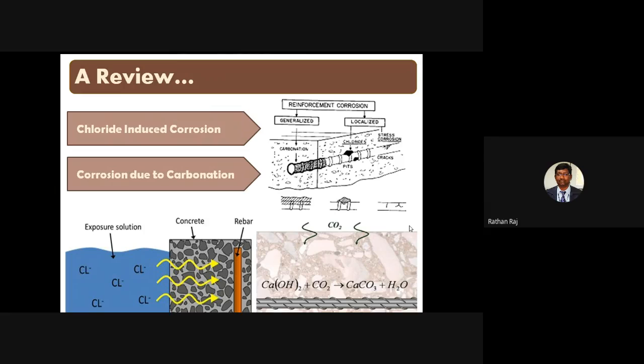Some calcium hydroxide is left in the concrete, as it does not react because sufficient water is not available. That calcium hydroxide will react with the carbon dioxide present in the atmosphere and convert to calcium carbonate. This is called carbonation. This takes place over years, but it is not the case with chloride induced corrosion. When the concrete surface is exposed to some de-icing salts or seawater, the chloride content will be absorbed by the concrete, reach the surface of the rebar, and immediately affect the passive layer on the rebar.